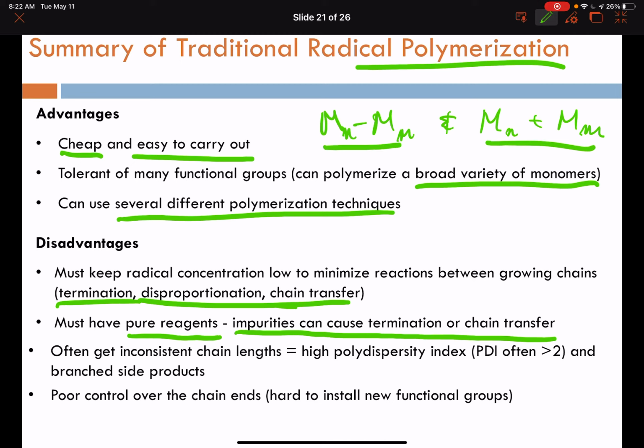So that is to say your molecular weight distribution will be broad, and you'll experience what's called a high polydispersity molecular weight distribution there. So this gives us poor control in molecular weight programming. And these radicals are quite reactive, and so some chain ends have to be managed carefully. So any reactive groups positioned too closely